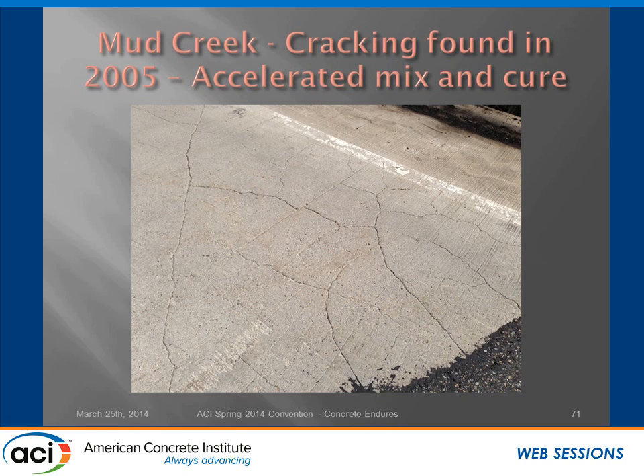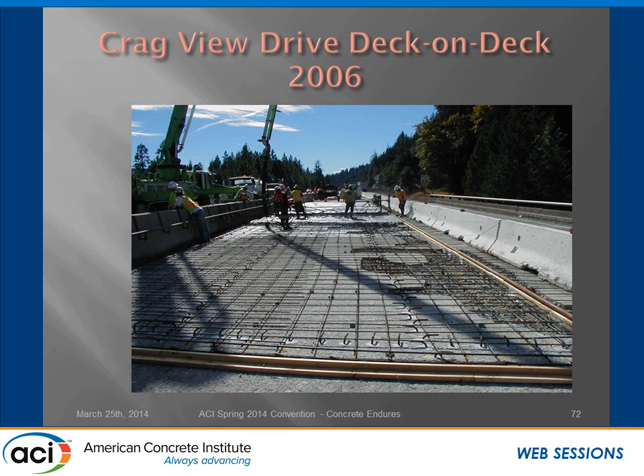And as you can see, the next year we went back and we found that that accelerated mix with the 3-day water cure kind of cracked up. And that's been pretty much our experience when we try to do these type of things. Interesting, though, the next year we had a very similar situation where we had a polyester overlay to go on an existing bridge deck on Highway 5 nearby this site.